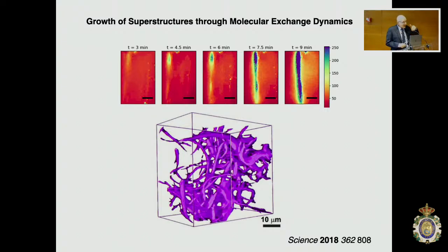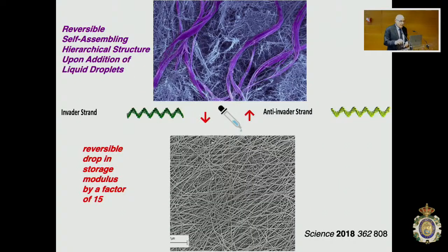They escape from the structure where they used to be, and they concentrate in other structures. And so then certain parts of the structure are strongly fluorescent because they contain all of the DNA, and then in the rest of the sample there's no DNA. You see that very clearly here.